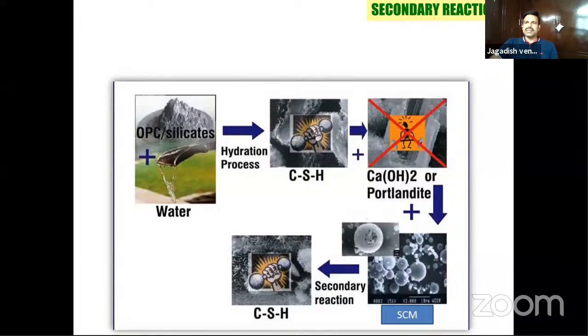Suppose you add secondary cementitious material, the excess lime present in the concrete will react with the supplementary cementitious material, whether you add fly ash or GGBS, whatever. And again, the secondary reaction will happen and it forms more CSH gels in the concrete. That means the excess lime that is present will react again with the supplementary cementitious material to form more CSH gels. That means the more dense the concrete, the more strength you will get.